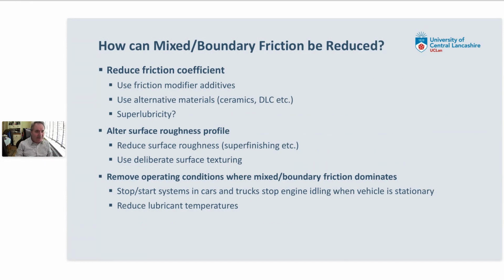The second thing you can do is you can try and alter the surface roughness profile. So you could actually superfinish components and reduce the surface roughness, but this obviously adds expense to the finished component. The other thing that you could do is you could put deliberate surface texturing onto components to increase the load-bearing capacity of the surfaces and actually increase the film thickness. And the third thing you could do is you could actually try and reduce the operating conditions where mixed and boundary friction dominates. So, for example, in cars and trucks, you will get most mixed and boundary friction occurring when the engine idles. So if you have a stop-start system in those vehicles where the engine stops when the vehicle is stationary, you effectively remove those operating conditions, and you will obviously reduce the amount of mixed and boundary friction. And the other thing you could do is you could reduce lubricant temperatures as well, and that will increase the viscosity of the fluid and increase the film thickness.